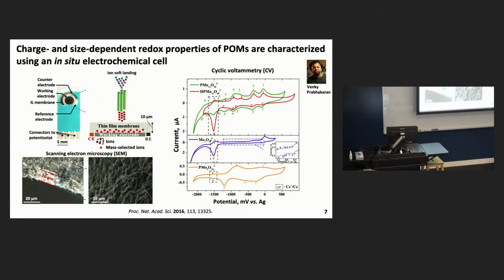So, as I mentioned, we were interested in the electrochemical properties of these clusters, so we needed a way to measure their redox properties and to do so in vacuum following deposition from the gas phase. So my colleague Venki Prabhakaran, who is an electrochemist, came up with a really clever idea of taking a screen-printed electrode, shown here, coating it with an ionic liquid membrane, which looks something like this in the electron microscope. And in so doing, this basically creates a conductive layer on your electrode into which you can then soft land your polyoxometalate ions. You can then attach a potentiostat and perform cyclic voltammetry measurements as shown on the right-hand side.